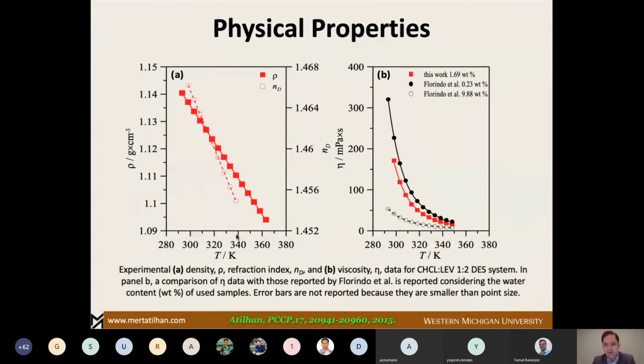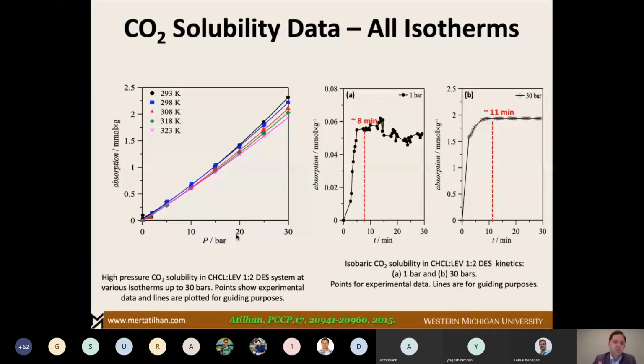So we dealt with the physical properties, density measurements and viscosity measurements. I'm not going to talk about them. But what was interesting for us, the main motivation, was the CO2 solubility data. At several different isotherms, we obtained up to 30 bars, around 2.5 millimole per gram of CO2. In the beginning, we were thinking, okay, we didn't hit the jackpot, but still there is an opportunity here.